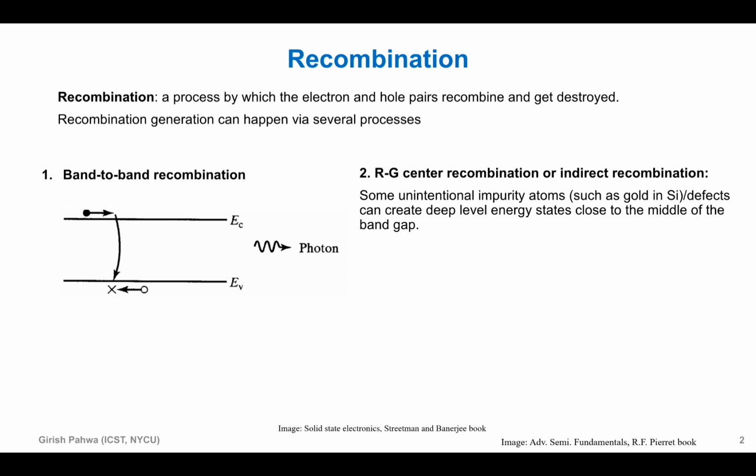In the fabrication process, say when you are growing the silicon, some of those impurity atoms will enter the silicon material, and now these atoms are discrete states. Usually they will give you some mid-level states, usually donor or acceptor. Where are those donor or acceptor states? Either close to the conduction band or close to the valence band. Whenever you have states close to the conduction band, say donor states, they can donate the electron. Whenever you have acceptor states, they can accept the electrons and create holes.